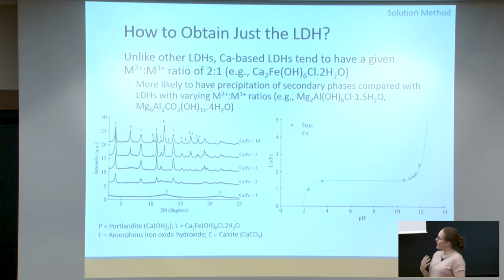So if we actually do this experiment whereby we go for different ratios for the starting solutions, we can measure the equilibrium pH. And that's what these crosses here are. They're experimental results. And then Maria has come up with equations to explain these experimental results, and that's given by the dotted line here.